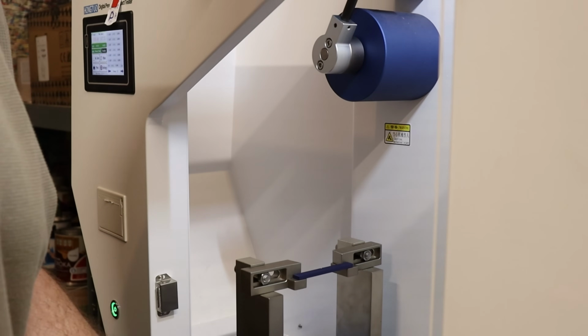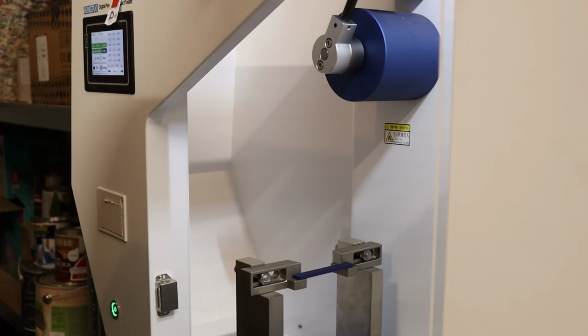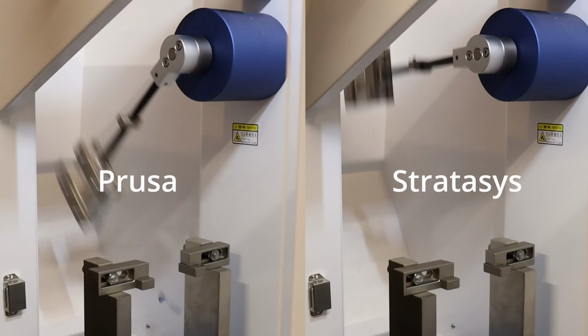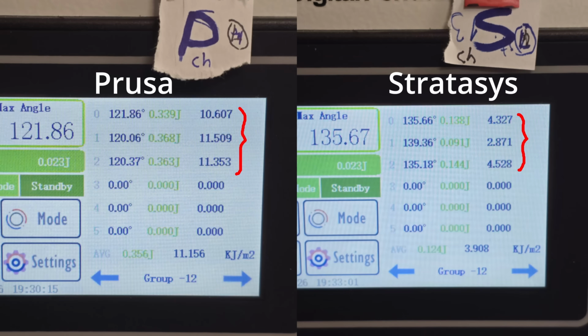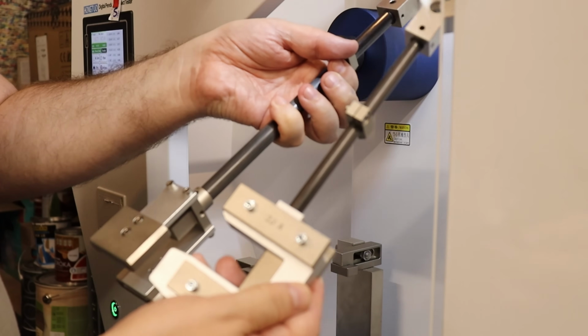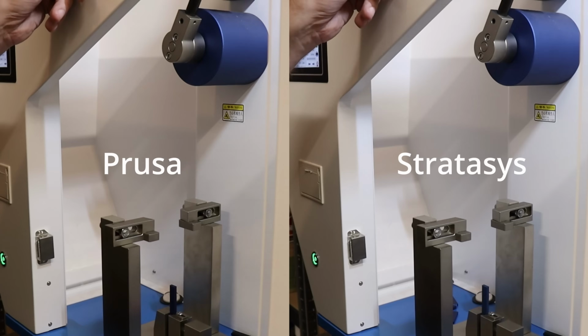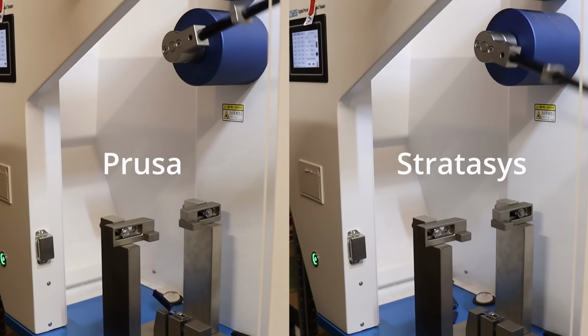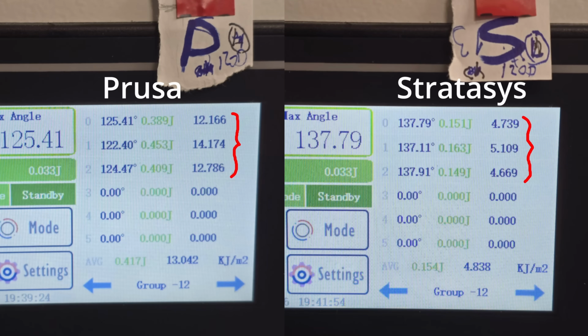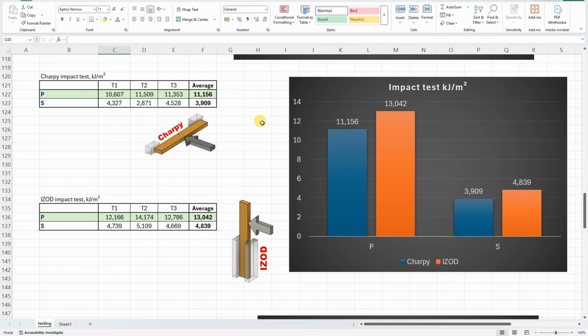Impact resistance is important for these materials, and I'm starting with the Charpy testing. Result from 3 measurings. Switching to the ISO hammer. Again our results, but let's see them on the graph. I think this property is important for ABS and ASA materials because this is a big advantage compared to any other filament type. The Prusament has acceptable impact resistance, but the Stratasys is very brittle, almost like some PLA or PETG.